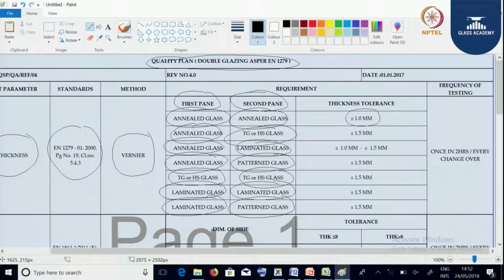When the glass combination is annealed and toughened or HS glass, the overall thickness tolerance is plus or minus 1.5 mm. When the glass combination is annealed and laminated glass, the thickness tolerance shall be plus or minus 1 mm to plus or minus 1.5 mm.